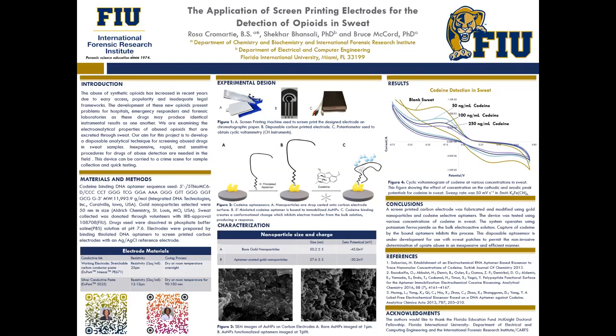So in the first table that you see under characterization, we're able to characterize the nanoparticles by size and charge, comparing both bare gold nanoparticles with the aptamer coated gold nanoparticles. It can be seen in this chart under size that the aptamer coated gold nanoparticle size increases when compared to the bare gold nanoparticle. The change in size demonstrates that there is an addition of DNA and shows that DNA has bound to the gold nanoparticle because of the gold and sulfur strong binding energy from the thiolated aptamer.